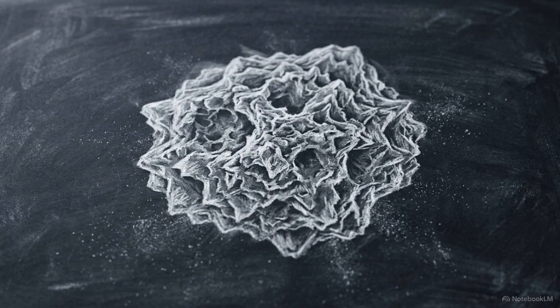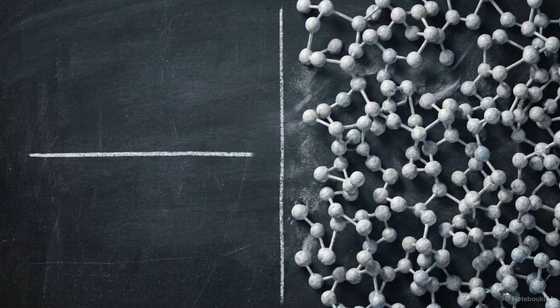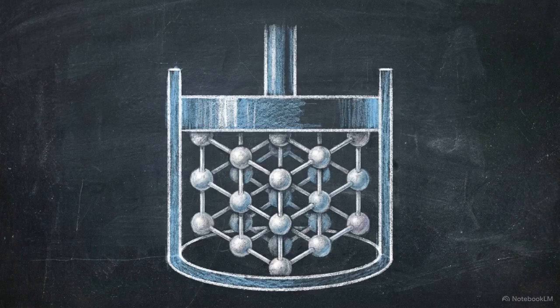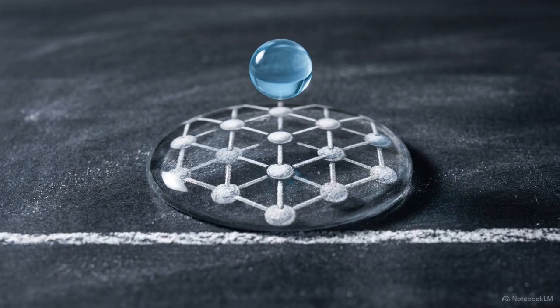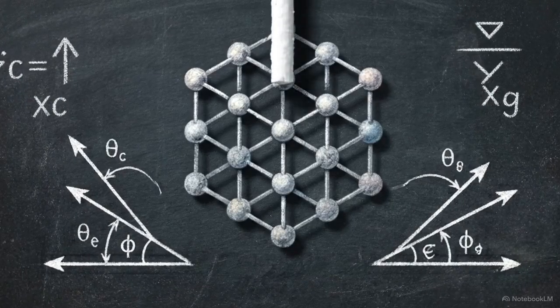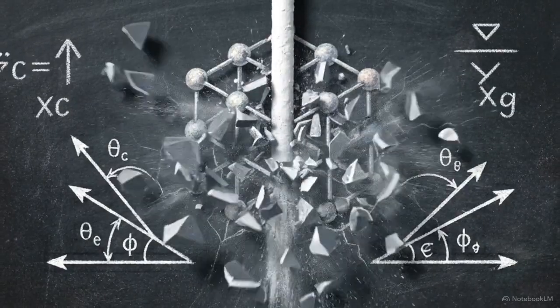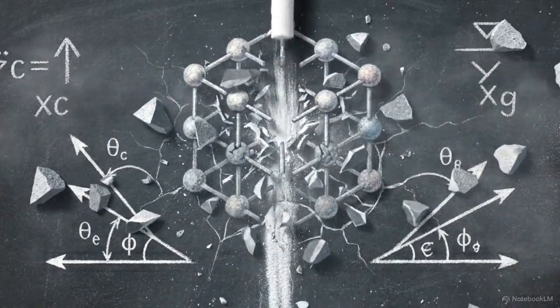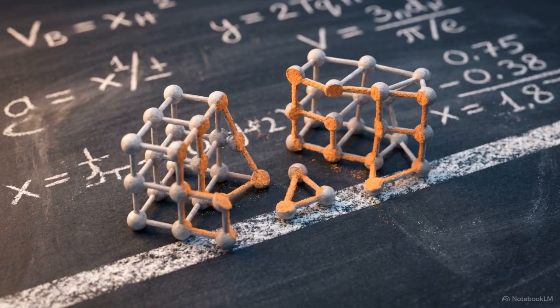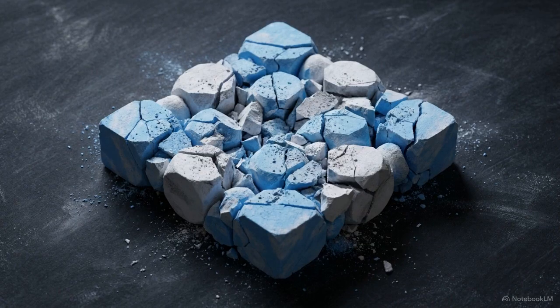There is a critical mathematical flaw in applying this geometry directly to pharmaceutical powders. The equation assumes an ideal, perfectly flat and smooth testing surface, something raw powders simply do not have. The standard industry workaround is to brute force the geometry. Technicians compress the powder into a tight, flat pill, creating an artificial plane they can drop a liquid onto. But the mechanical process of compaction forces the particles through brittle fracture and plastic deformation. It shatters the crystals, exposing entirely new, high-energy surfaces that skew the true contact angle data. By pressing the powder to measure its surface energy via traditional contact angles, you physically destroy the exact property you are attempting to measure.